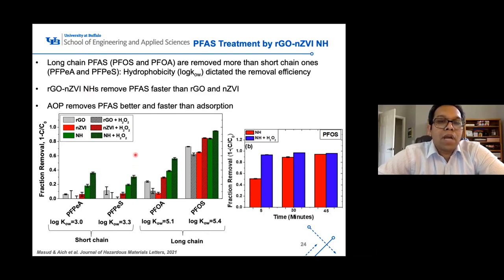The other thing is we are testing between hydrogen peroxide and without hydrogen peroxide. So AOP, advanced oxidation process, is removing better and faster than the adsorption process. If we look at the overall difference, this is the nanohybrid with hydrogen peroxide and this is the nanohybrid without hydrogen peroxide. Even if we look at the time, within 5 minutes, with nanohybrid without hydrogen peroxide, just by adsorption, we are getting 50% removal, whereas almost 90% removal with hydrogen peroxide. So that's what the difference is. So we are seeing the catalytic activity of the nanohybrids here.